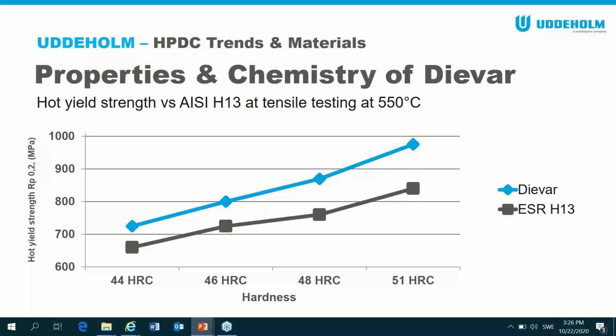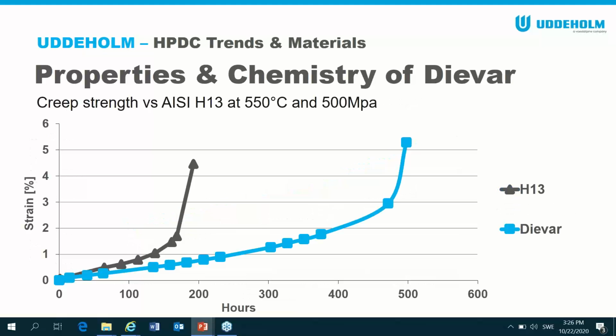Another property you need is hot yield strength, which is what I mentioned earlier. So this is a tensile test at 550 degrees C. And you can see at 51 Rockwell there that ESR H13 has about 830 megapascal, and Dievar has just under 1,000, about 970, 980. So again, big difference in hot yield strength.